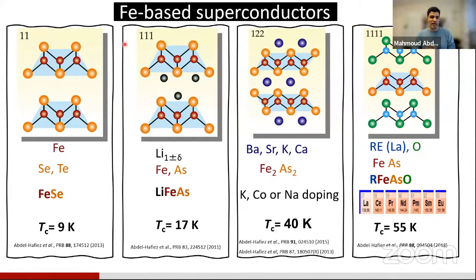If you look at the 11 and 111 systems, they are layered structures. These layered structures are superconducting without any doping. That's interesting, because if you put ions in between, you also get superconductivity. However, in the 122 and 1111 systems, the undoped material is not superconductive. So you have to dope the material, you have to remove electrons from them to become superconductive, or you have to put the material under pressure to induce superconductivity. The highest Tc here we achieved is up to 55 Kelvin.